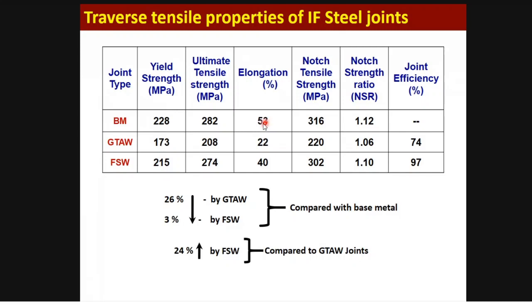But the elongation, you see that the base metal elongation is 53. That's why it is easy to friction stir weld IF steel, large elongation. But in the GTW, you see that the elongation is greatly reduced to 22%. But here in FSW, though it is less, when compared to the TIG welding it is much higher, and it is coming close to the base material. So that's why the joint efficiency, you see that 97% in the FSW joint, only 3% less compared to the base metal. That's a great advantage of this process.